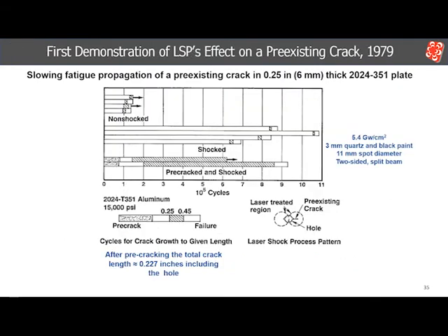Here is the first look at how laser shocking the tip of an existing crack effectively slows its propagation. This was done on 2024 T351 plate, 6 millimeters thick. As shown in the illustration on the bottom right, a central hole in the gauge section of a test specimen had notches machined into it on both sides. In one set of tests, a laser spot was applied centered on the hole, not shown in the illustration.